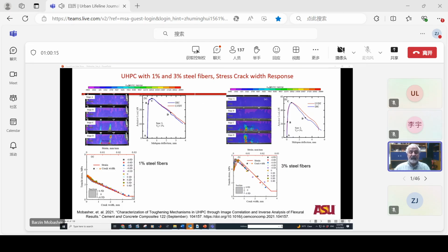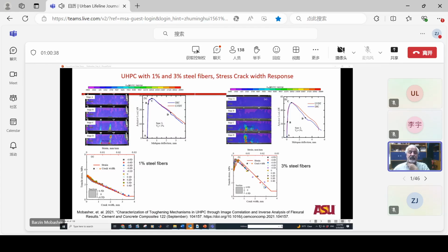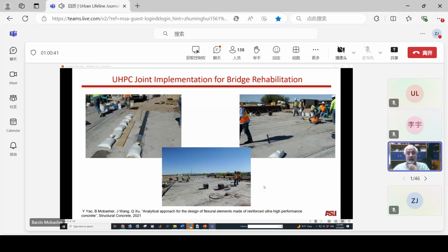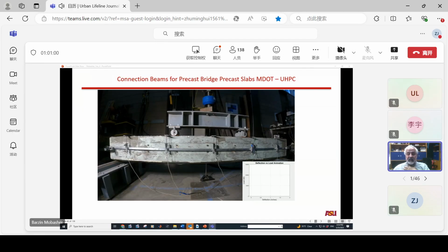We can actually measure the strain softening response or strain hardening response. With 1% fiber, you only need about 5 megapascal tensile strength and this large range of softening to be able to get this response. With 3% fiber, the stress strain curve changes, but still we get much better performance. So these are some pictures of the fact that you can replace a bridge in 3 days, which is just wonderful, especially in some rural areas where an entire community depends on a bridge to be accessed. So these are some tests.